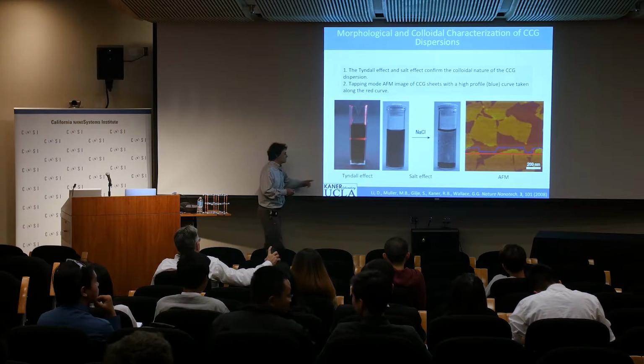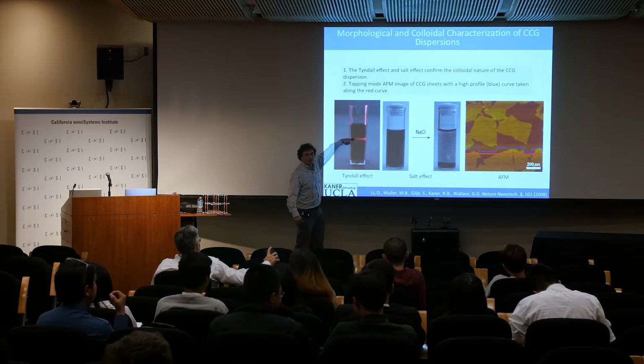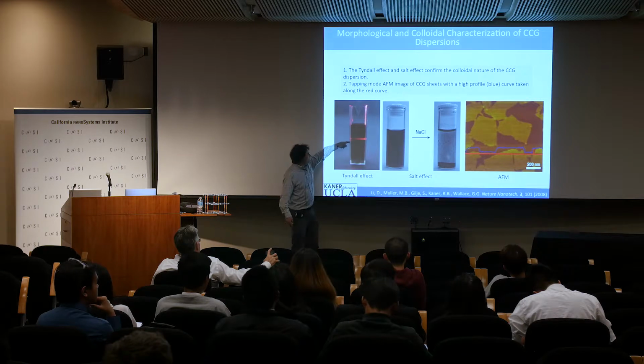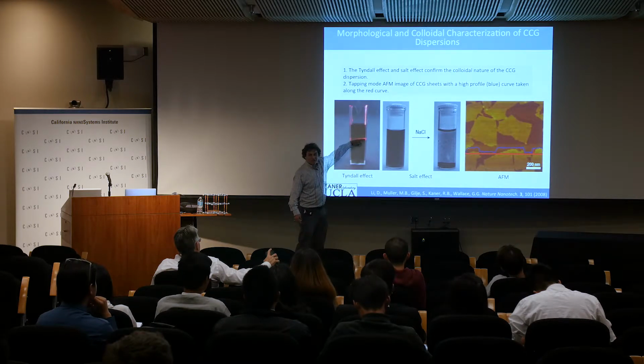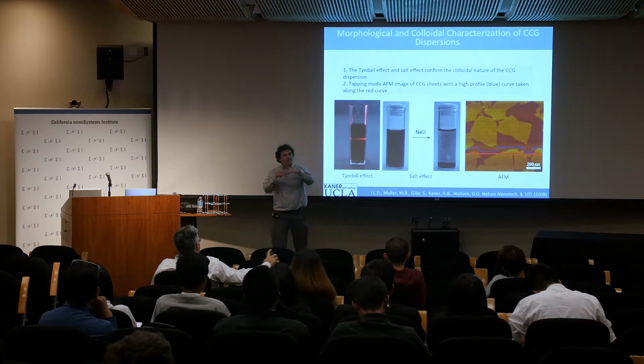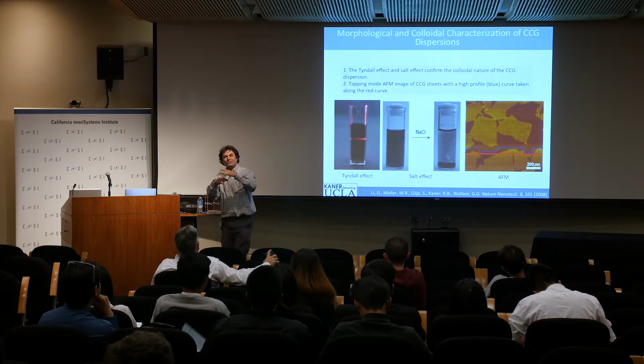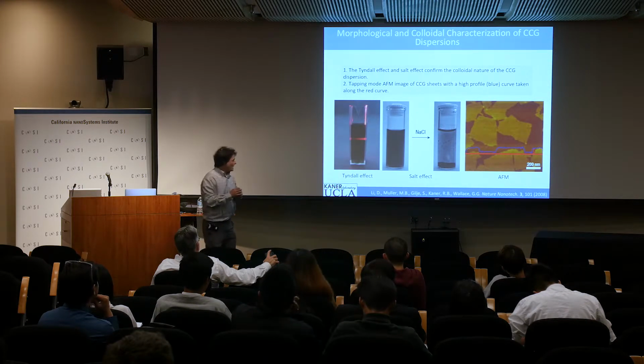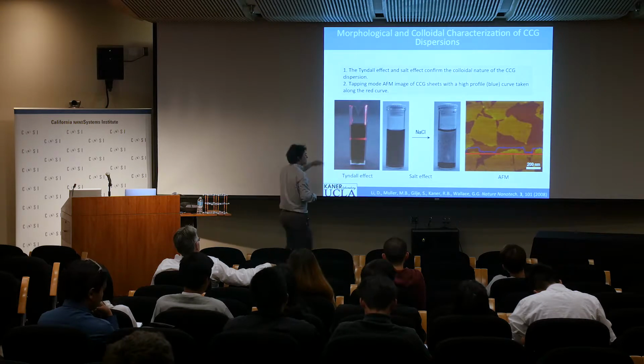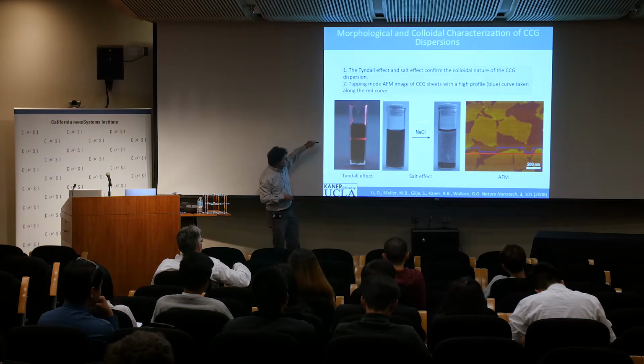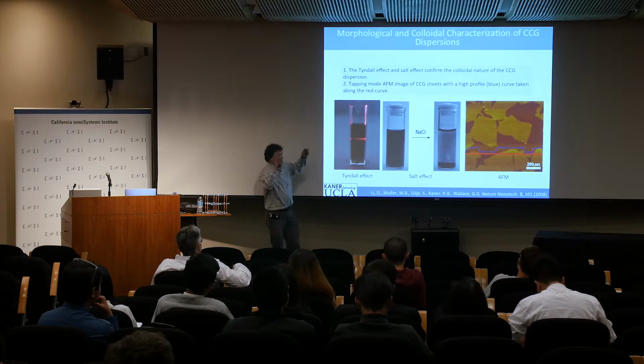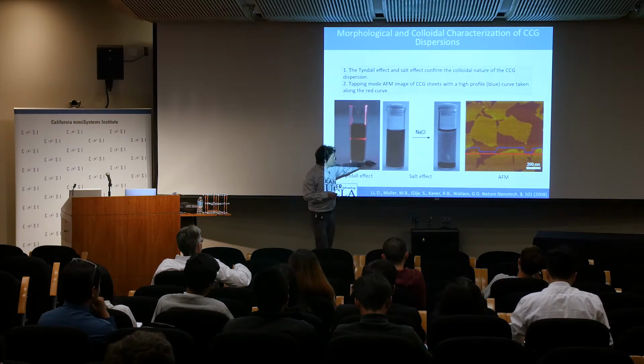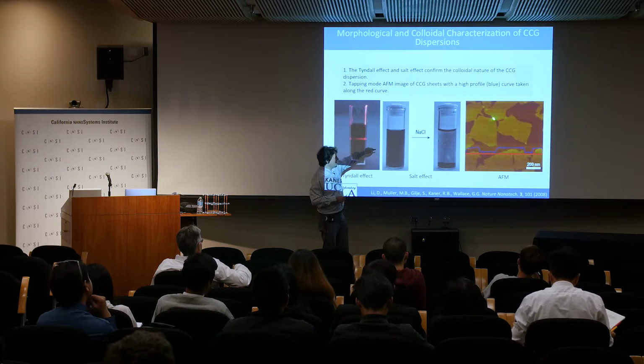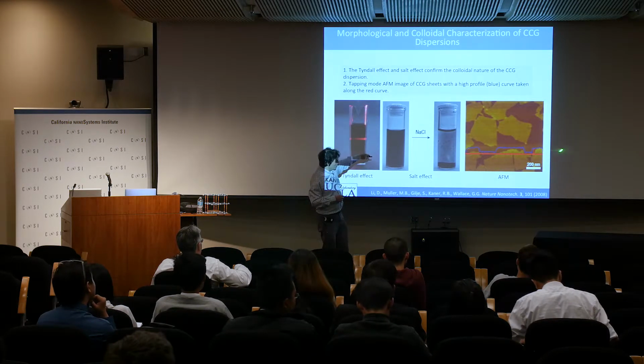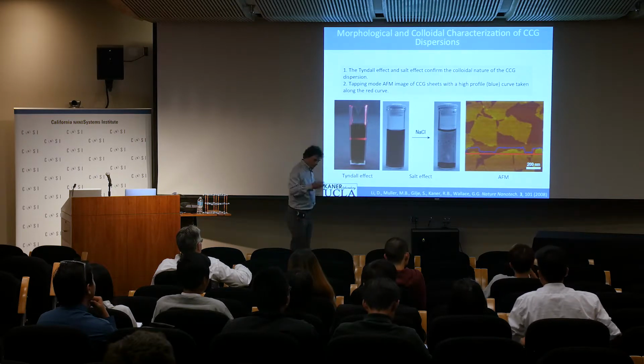The way you can tell that, it shows the Tyndall effect. If you put a laser in, for a solution, the laser goes through, but you'll notice you can see the red laser, it scatters light. And so literally, it's single sheets, and they all have the same negative charge on their surface, so they stay apart. How do I know that? Well, if we neutralize the charge, we can put in salt like sodium chloride, it falls out. Because that neutralizes the charge on the surface, they fall out. And here are pieces by atomic force microscopy of chemically produced graphene. And you can see it's on the nanometer scale.